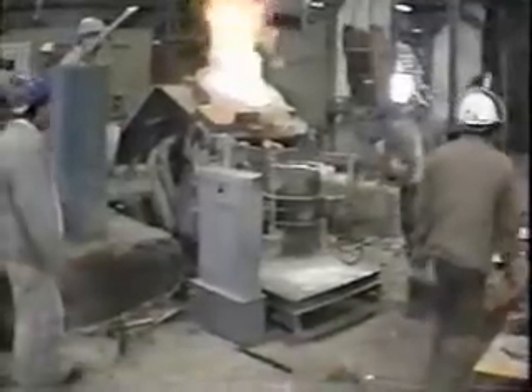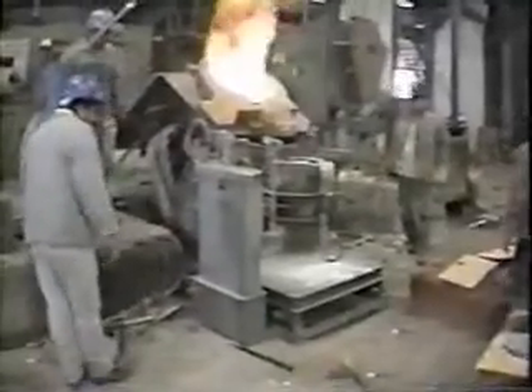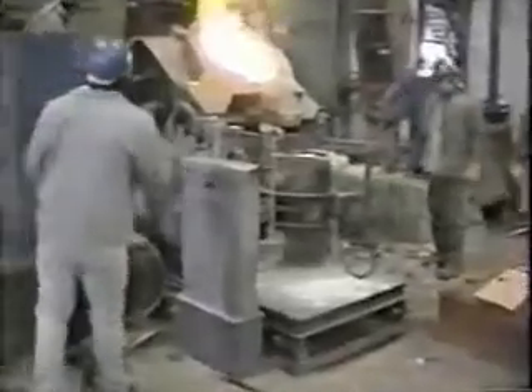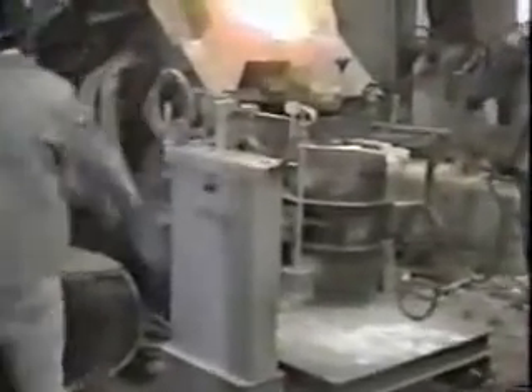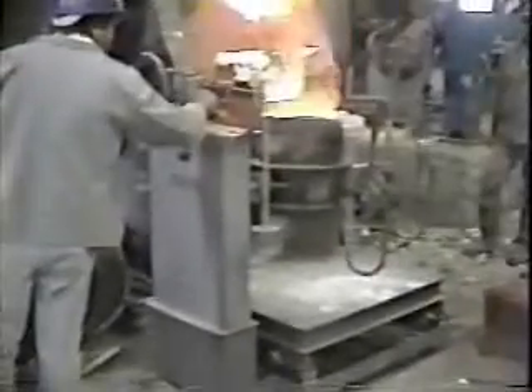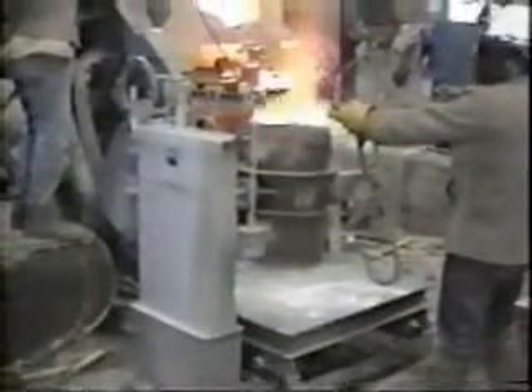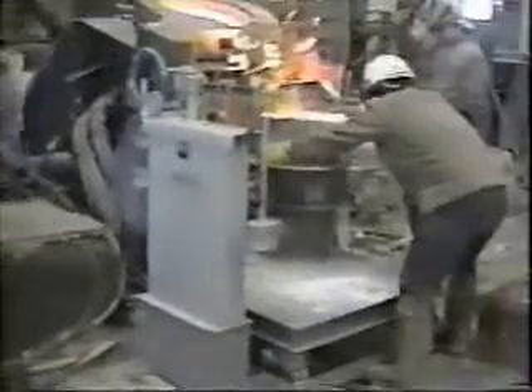A smaller ladle is used now because we're weighing a smaller amount, and the scales is placed in front of the furnace for more careful weighing of smaller amounts of metal. Since all the metal is poured into the mold and there's 100% yield, the final thickness of the casting is determined by the weight of the metal poured.